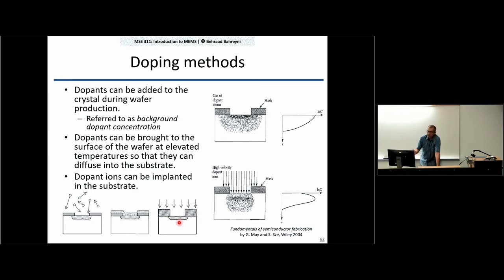Well, you cannot shoot atoms. It's not easy to shoot atoms. What we do is that we ionize them and then accelerate them in an electrical field and then aim them at regions that we want to dope. Because these are high energy atoms, or ions, they do not stop at the surface. Usually they go a little bit below the surface and stop there, right?